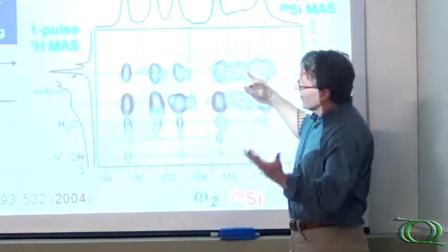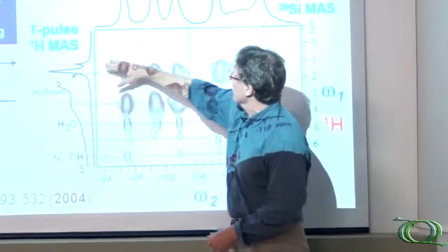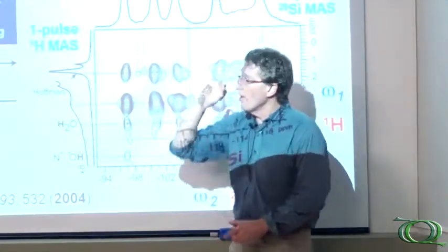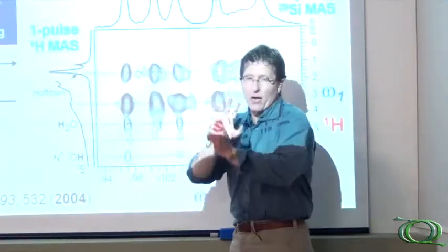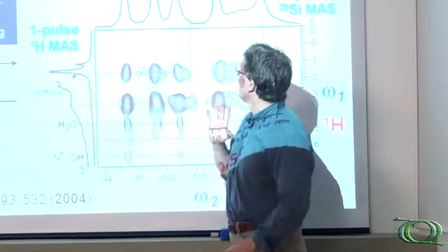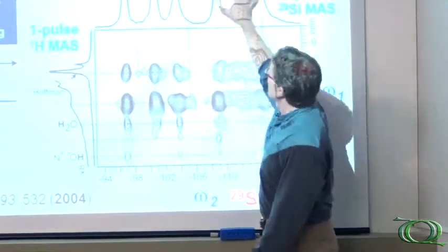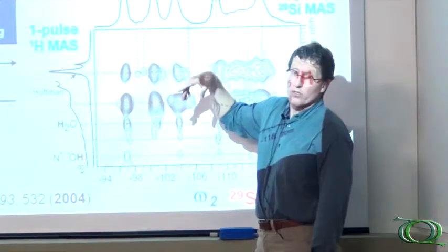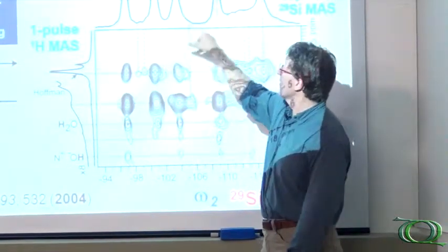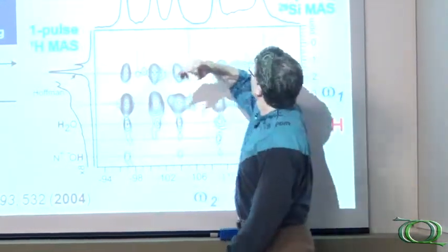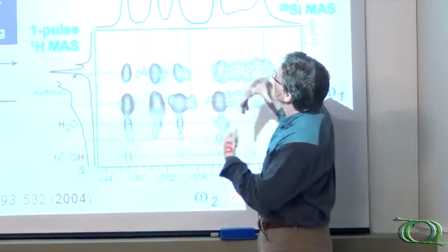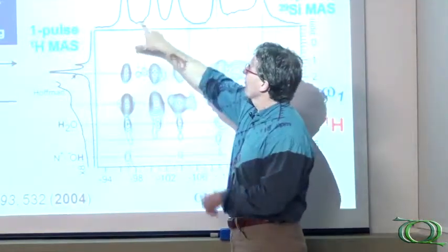And so we see, in this case, a long contact time, and therefore we see couplings amongst them all. So one of the things Helmut was suggesting is that you can use a contact time which is short and thereby get only the strongest couplings and just exclude the weak ones. Now, it turns out that in these layered silicates, they're all very close to the surfactants, so it's not a strong difference. But you do see these Q3 and Q4 species, which actually now are prevalent.